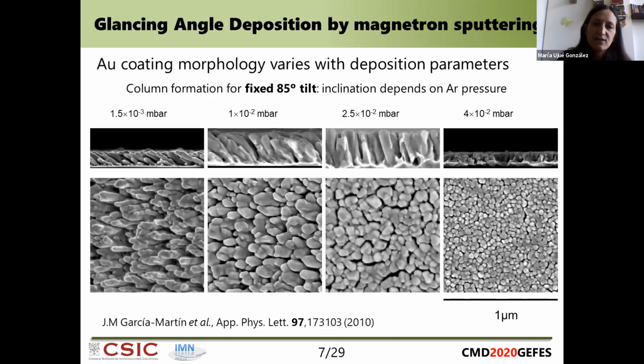So when we play with all these conditions, there is a huge amount of parameters that can allow us to modify the morphology of these nanocolumns and the kind of structures that we can obtain. As an example here, this is a gold coating that has been made by fixing the angle between the substrate and the target at 85 degrees. This is fixed, but we have changed the argon pressure, and it's increasing. And as you see, we go from very tilted columns to less tilted and a much more compact structure when the pressure is higher, and then there is less directionality.